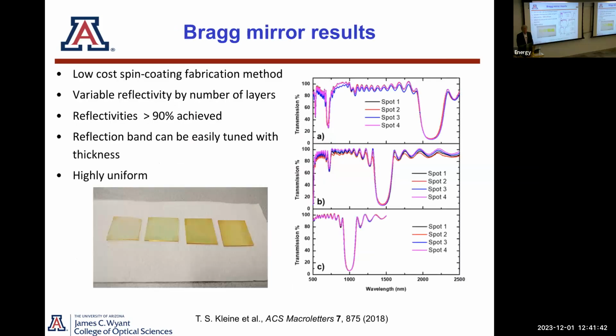And we made mirrors. The student who did all the spin coating, I was very impressed with her work. This was about 20 layers that you had to spin coat, using the process we use for lithography to make these coatings. And with a Bragg mirror, you can move the peak reflectivity around just by changing the thickness, which we showed very nicely here. That was a nice early demonstration of the thin film capabilities of these materials.